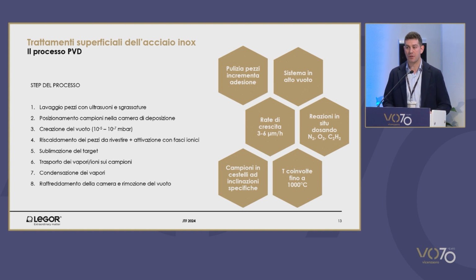The sample is then placed on baskets in the deposition chamber. The baskets are oriented so as to promote the adhesion of the coating. Vacuum is generated with a pressure between 10^-5 and 10^-7 millibar. The target is transformed into vapor, and the metals are then deposited on the substrate. Afterwards, the chamber is cooled down. With these systems, at times you can have reactions, with the deposition of the metal together with a gas which is not inert but reactive, as in the case of nitrogen, oxygen, or acetylene. You might create on the substrate carbides of the metal